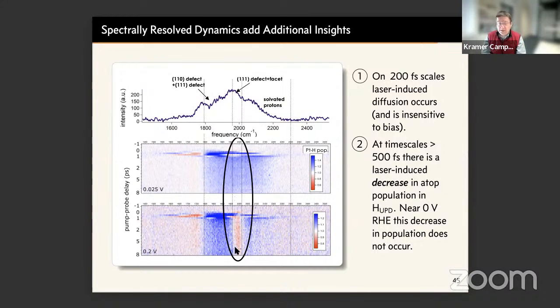There is no communication, right? The simplest interpretation of the signal is that there are multiple different types of surface hydrogens, and that within the UPD, most of these can exchange on few picosecond timescales, but that there's something special going on with these 1-1-1 facet frequencies. This special quality, whatever it is, is removed as you approach 0 volts versus RHE. So now here, apparently this type of structural site can communicate on ultrafast timescales with all the other sorts of atop adsorbed hydrogen. Okay, so where does this leave us, right?